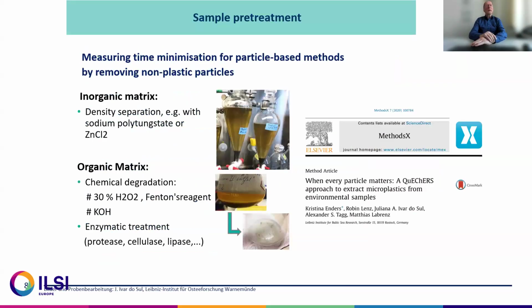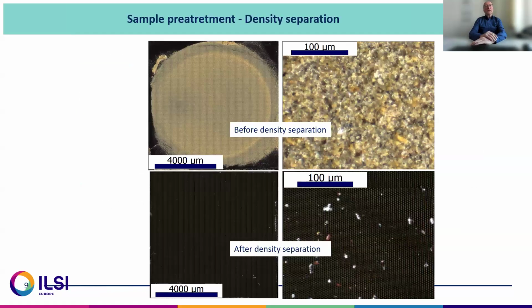To the sample pretreatment, mostly if you have an inorganic matrix, you need a density separation. And for removing organic matrix, which is very often in food samples, you can use the Fenton's reaction with peroxide. You can use KOH, but mostly you have to use it to remove fatty acids and so on, and enzymatic treatment by different cellulases, lipase, protease, and so on. This should show you why we use a density separation for the inorganic matrix. Often you see a filter before and after the density separation, and you can imagine an analysis without it is not possible.